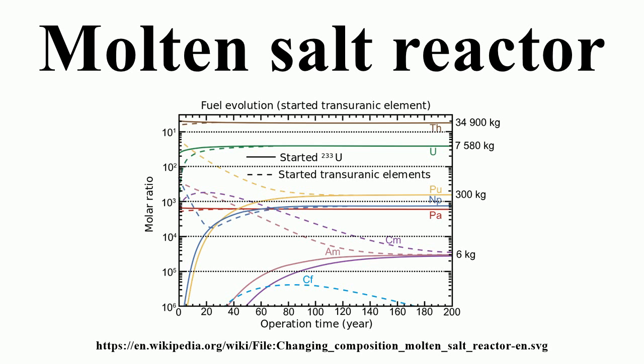After the ARE, another reactor was made critical, at the Critical Experiments Facility of the Oak Ridge National Laboratory in 1957 as part of the Circulating Fuel Reactor program of the Pratt and Whitney Aircraft Company. This was called the PWAR-1, the Pratt and Whitney Aircraft Reactor 1. The experiment was run for only a few weeks and at essentially zero nuclear power, but it was a critical reactor. The operating temperature was held constant at approximately 675 degrees Celsius. Like the 2.5 MWth ARE, the PWAR-1 used NaF-ZrF4-UF4 as the primary fuel and coolant, making it one of the 3 critical molten salt reactors ever built.